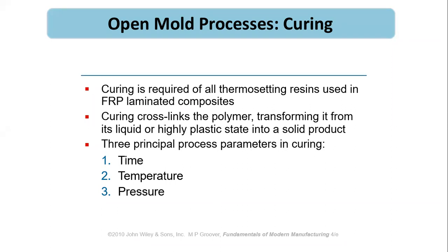Some resins are cured at high temperature, and some resins are cured at room temperature. Some resins take like 1 hour to cure, and some of the resins take like 24 hours to cure, or more than that. So time, temperature, and the pressure. If you put it at very high pressure, then the temperature might be required less. So these are the controlling parameters for curing the fiber reinforced plastic composites.